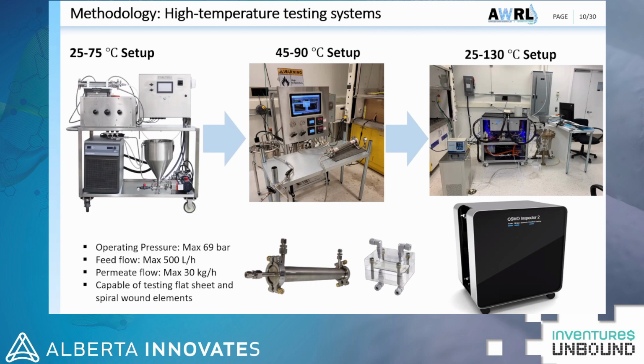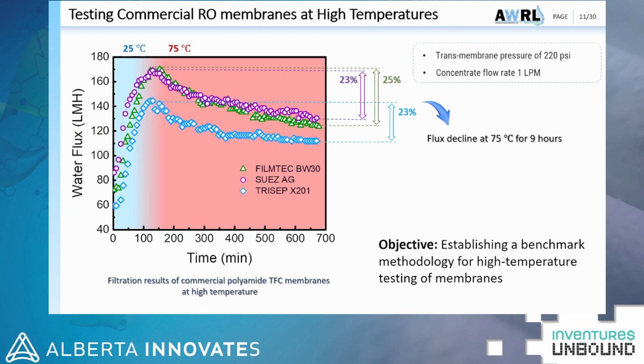We first tested the commercial TFC membranes to establish a standard operating protocol for high temperature testing of membranes. As you can see, the flux of three commercial membranes decreased gradually at 75 degrees C. Less flux decline over time is usually considered as a criterion for thermal stability of membranes. So here we can see that we have up to 25% flux decline at 75 degrees C for the commercial RO membranes.